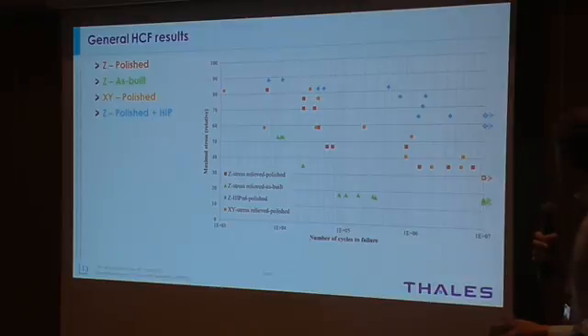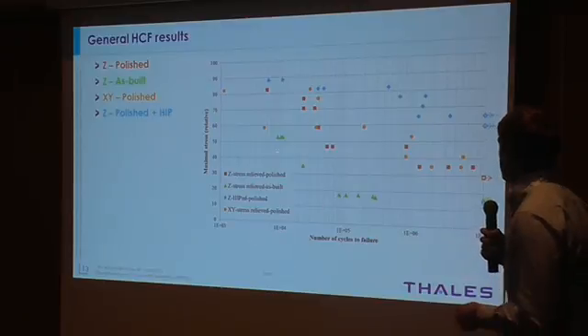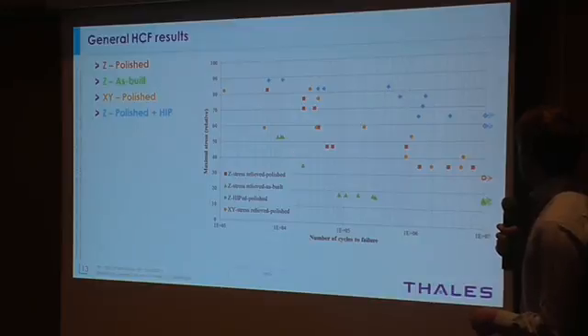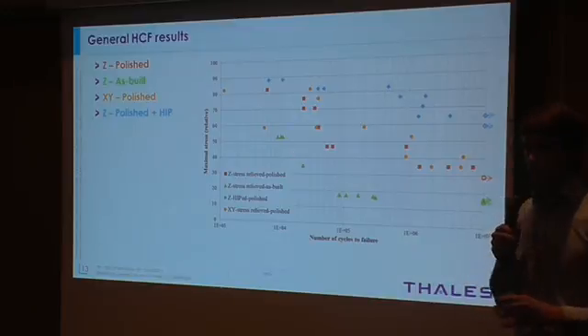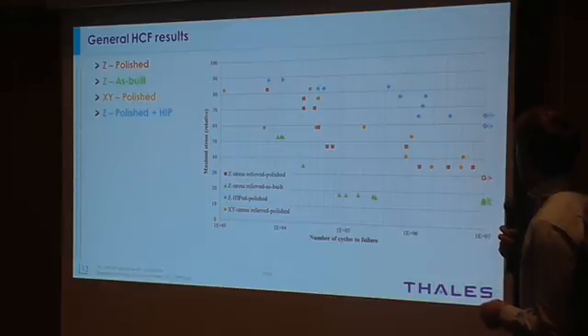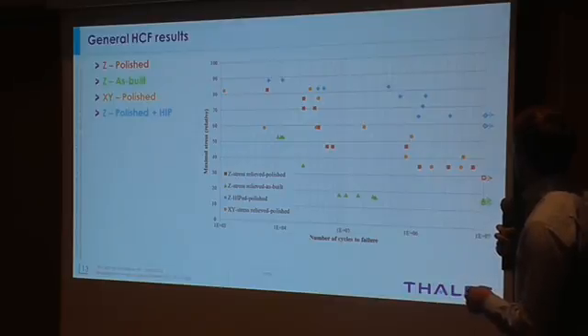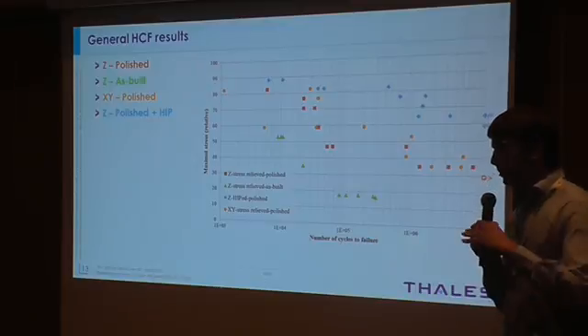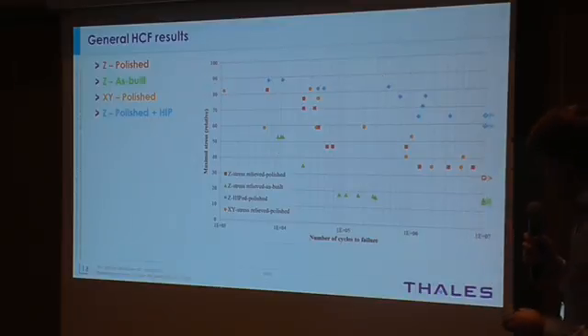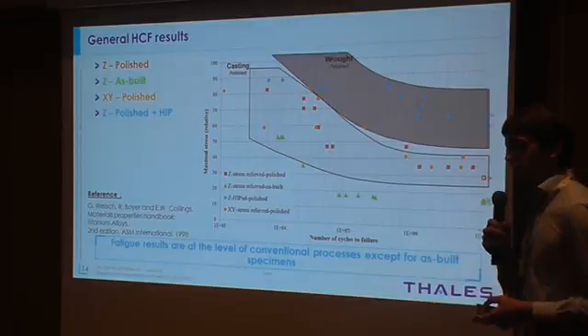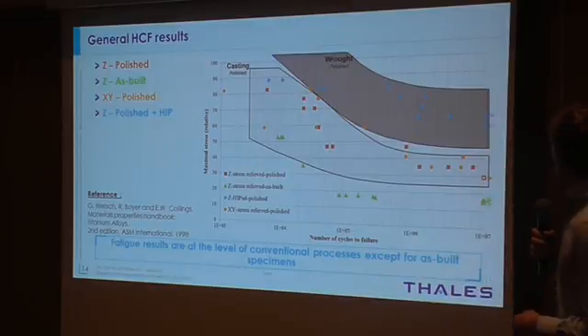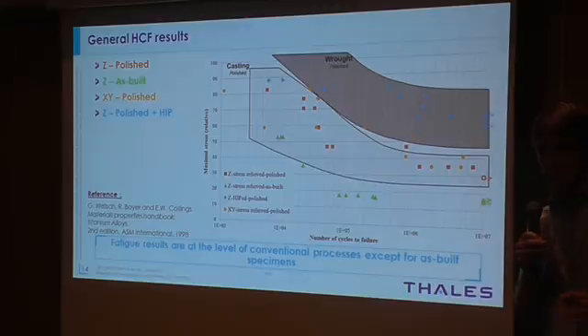So here are the points. We can see that as built in green is in the lower part of the diagram. Z and XY are in the middle, and in red and orange, and HIP specimens are on the top of the diagram in blue. We compared with the one reference on conventional processes. So we can see that in the X, Y, and Z direction, we are at the level of casting, and after HIP, we are at the level of wrought processes. So it's good result for that.